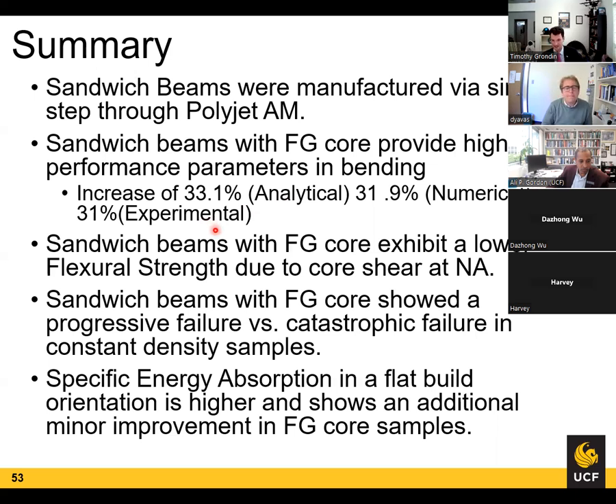We had a great experiment, and we also found that there was a lower strength, which we knew was going to happen. So a design trade-off there for future work. And then we also found the progressive failure possibilities in the functionally graded beams. Finally, we inadvertently found an awesome specific energy absorption in the flat build orientation, which was slightly higher in the functionally graded samples.